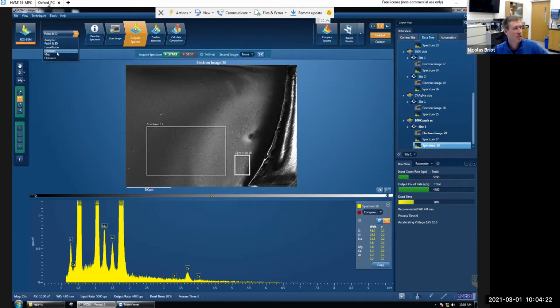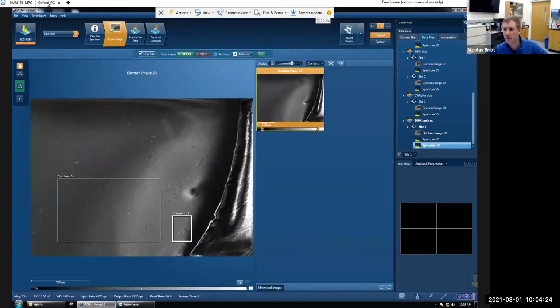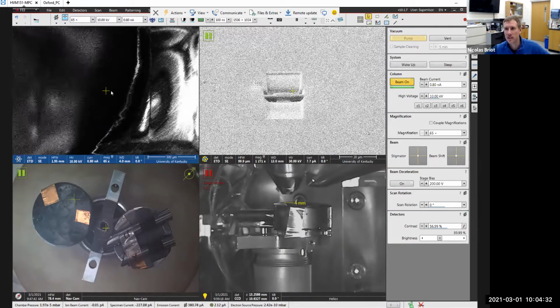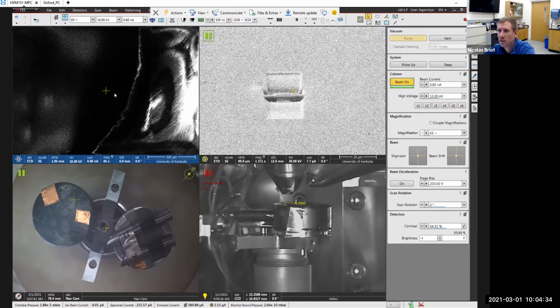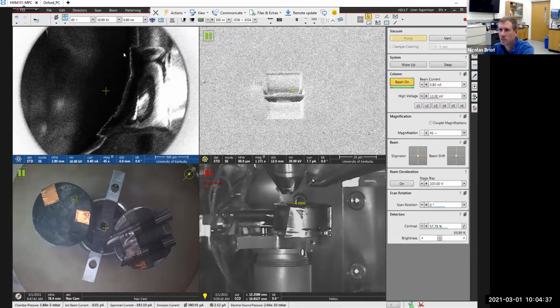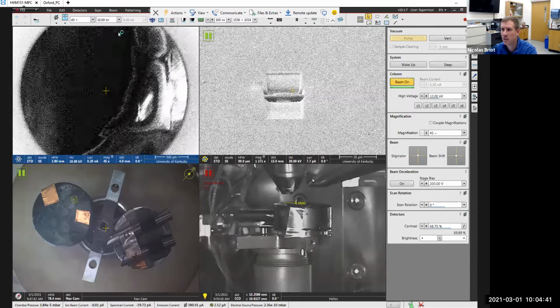So let's switch here to a line scan, and I'm going to go to the edge here. If you look at the scale bar, I say I'm close to the surface, but I'm still a few hundred microns from the surface. So that's actually really significant. Ooh, the charging effects are not good. So I'm going to go a little slower. Maybe you can get something a little better.